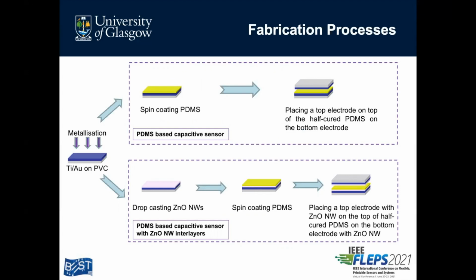We fabricated two PDMS-based capacitive pressure sensors with and without zinc oxide nanowire interlayers. The reason why we chose to use PDMS was because of its good thermal and chemical stability, effective dielectric property, biocompatibility, and excellent mechanical property to undergo a reversible deformation. At the start of the fabrication process, the top and bottom electrodes were prepared by depositing titanium gold on a PVC sheet.